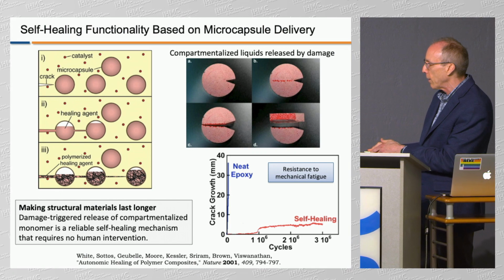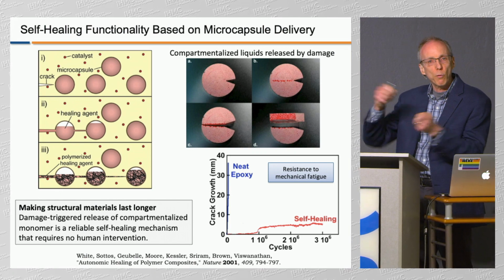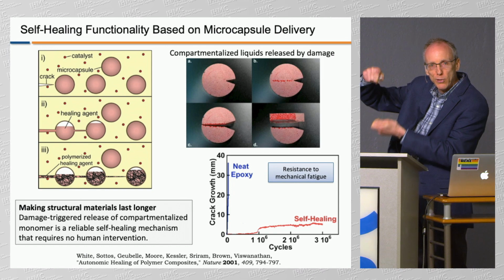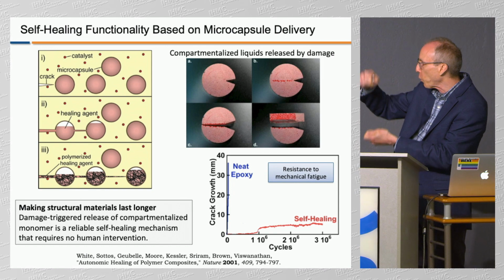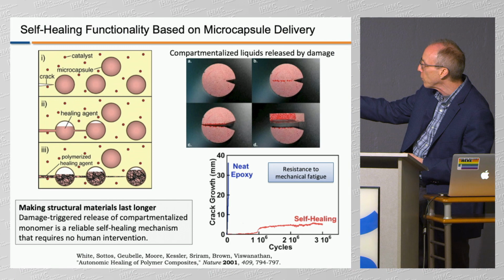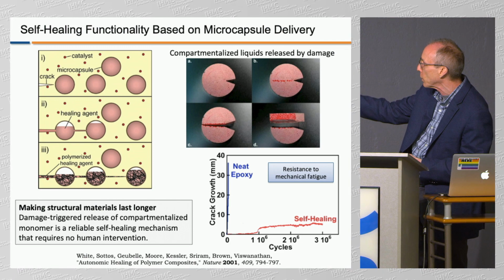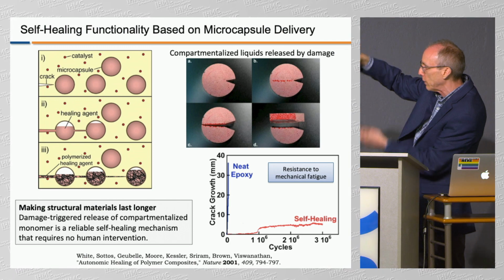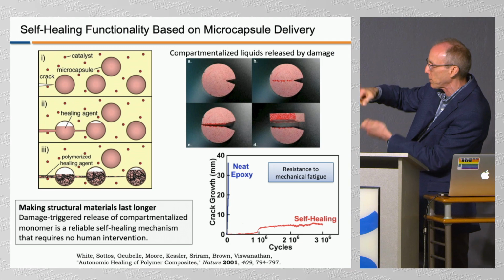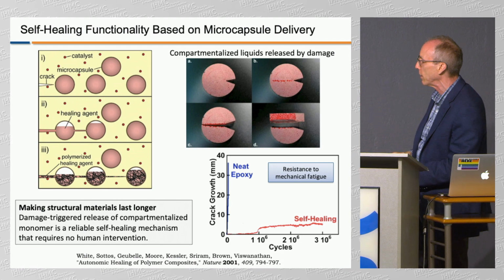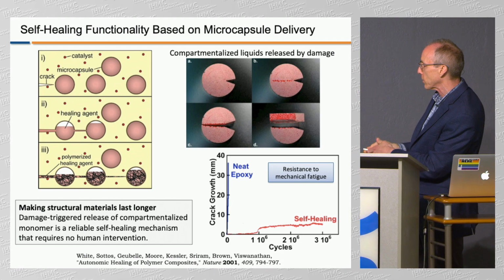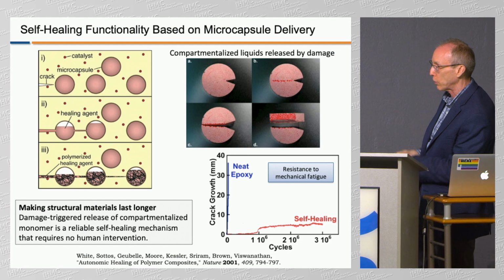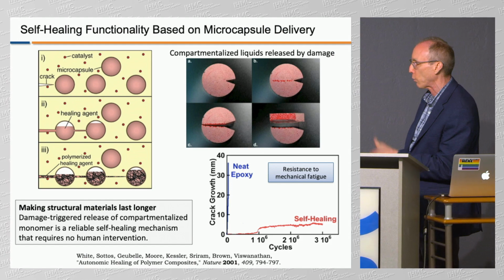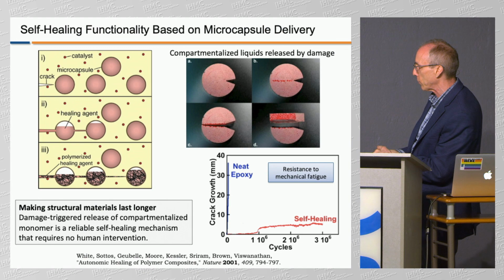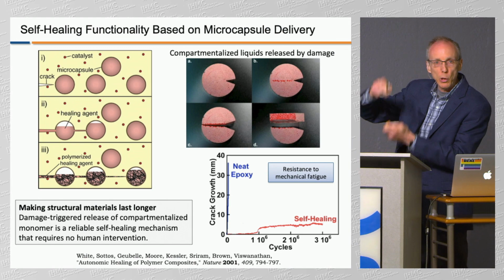We're looking at growing a crack by fatigue damage. We're basically causing, through oscillatory loading and unloading of a specimen, it might look like that, and the load would go in the vertical direction, but it would be oscillating, fatigue loading. And so how fast does that crack grow? In the control sample, the neat epoxy, it grows very quickly. This is the number of cycles that we've loaded and unloaded.